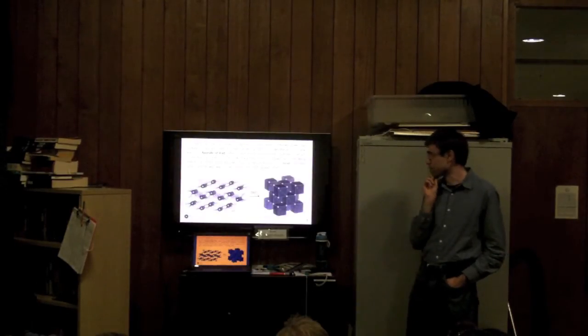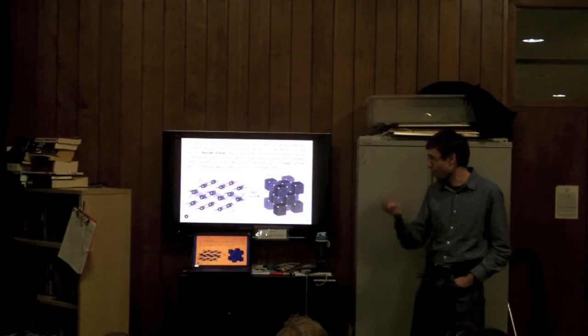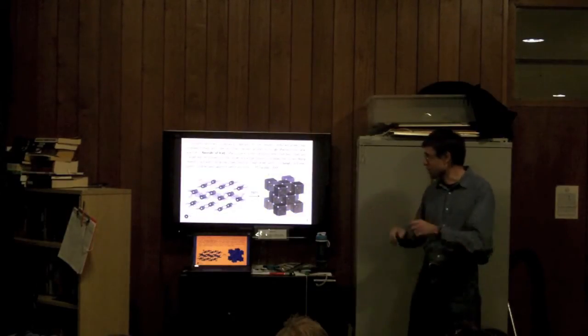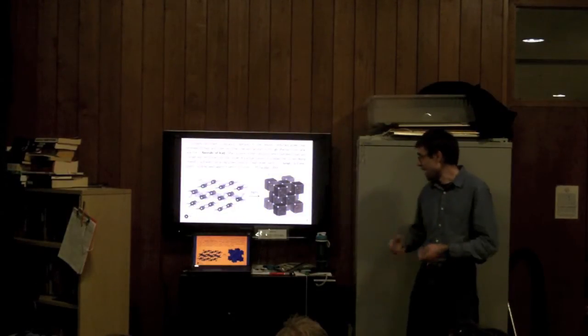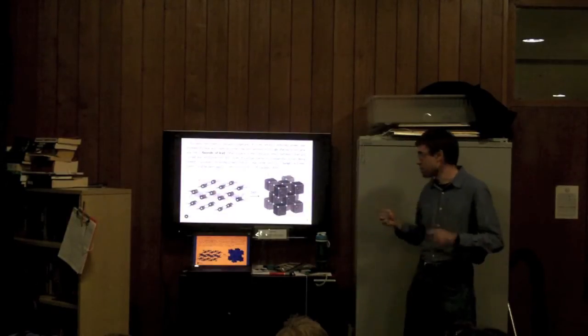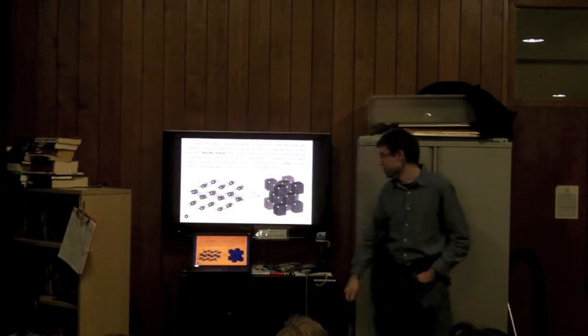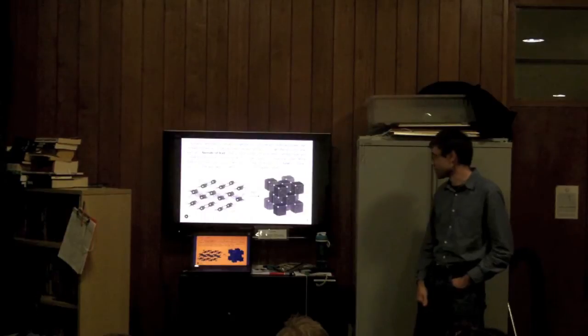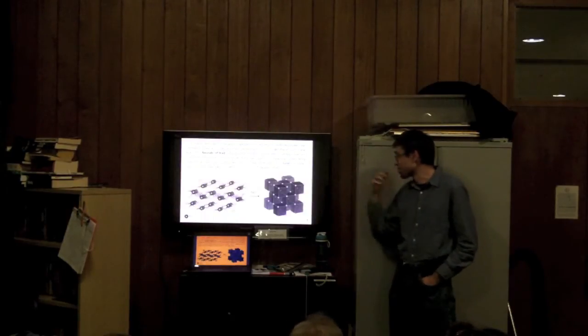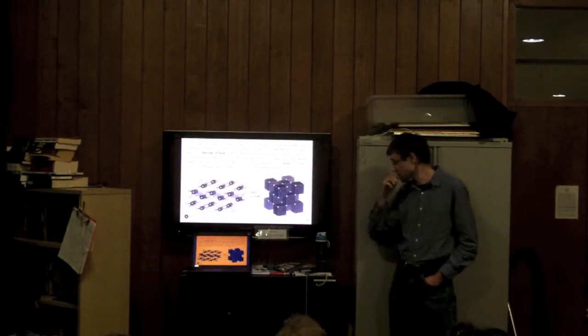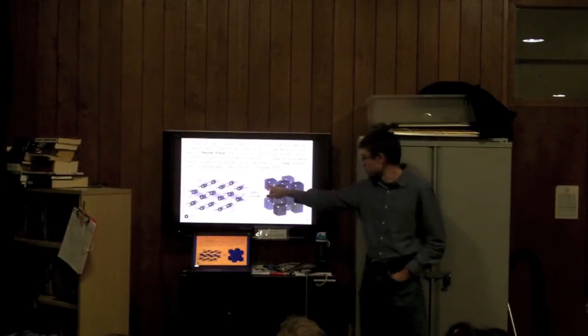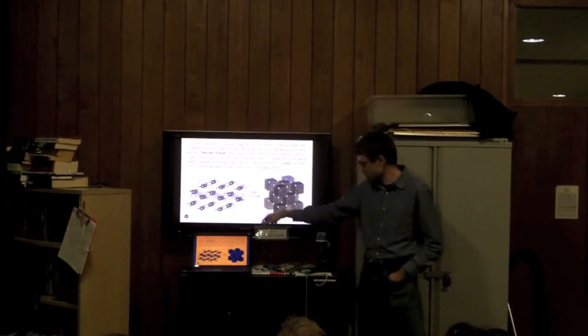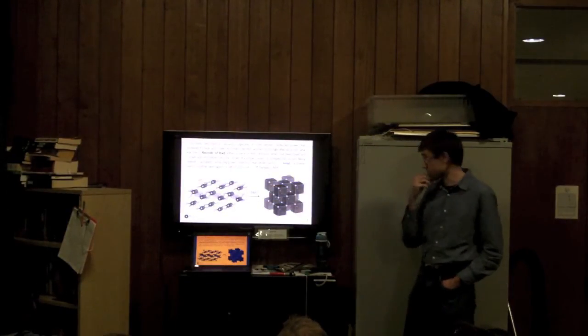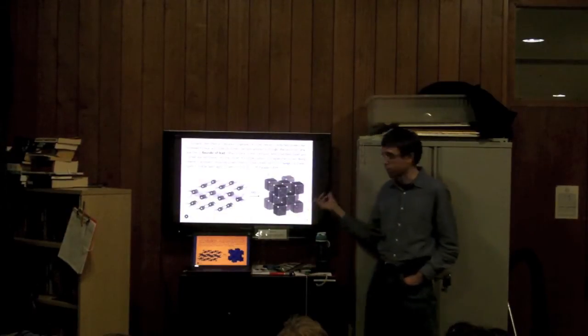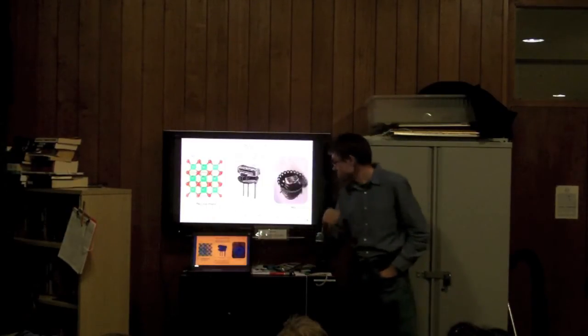Faraday, way back in the 1800s, took these incredibly toxic chunks of lead fluoride, put them between two bits of a battery, and nothing happened, except when he heated it up to 300 Celsius, which is also very dangerous to do, these would now start to actually conduct electricity. And they would do so because these fluorides would propagate through the structure. He had no conception of this at the time, but he was actually producing the first solid electrolytes.